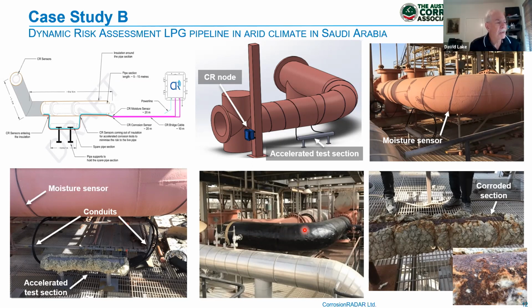So can it be installed further away and you still get meaningful results? So the sensors function normally. They can even function outside. We test them on a normal table. So they function normally. However, the assumption here is they should represent the corrosive condition or corrosivity of the pipe or the asset. So the closer we place them to the asset, the more realistic results they give. If we place them far away, then the conditions they detect will not be representative of the conditions seen by the pipe. So yeah, it's ideal to have it in proximity to the asset surface.